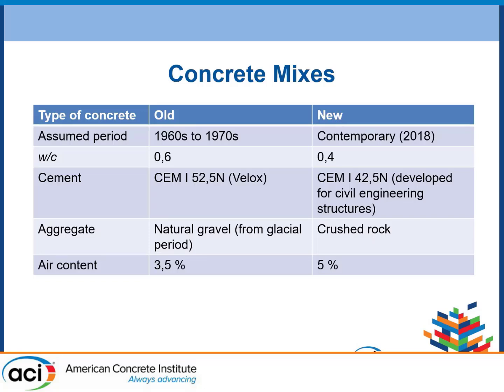Okay, so we tried to estimate a concrete of the type that was used in the 1960s, and at that time we used a water-cement ratio of 0.6. I'm not very familiar with your classification of cement, but CEM I, according to the European standard, is a Portland cement containing at least 95% Portland cement, and then the other is gypsum. So that was used, and almost a similar one nowadays. But we have a little bit larger cement particles now than before.